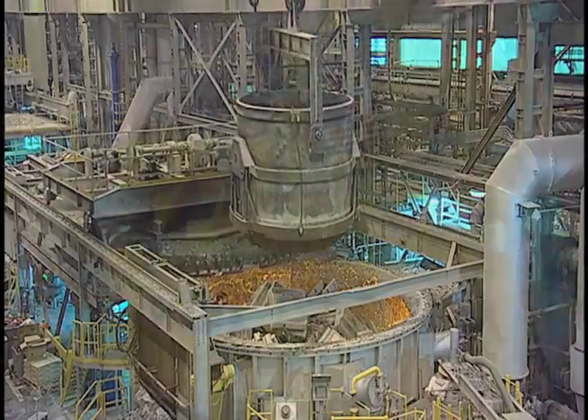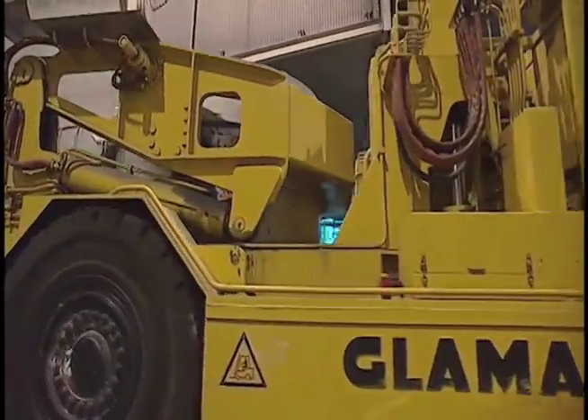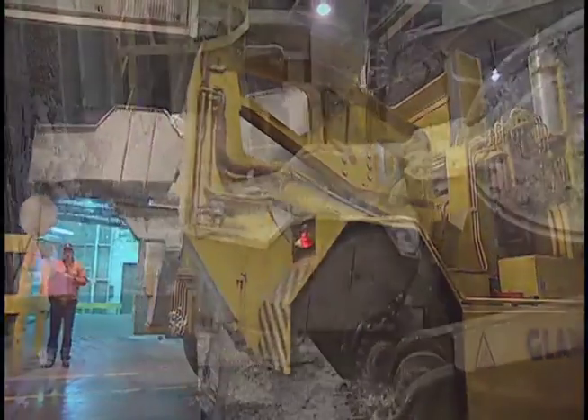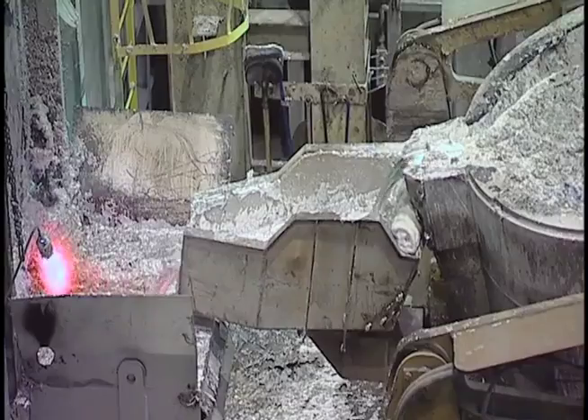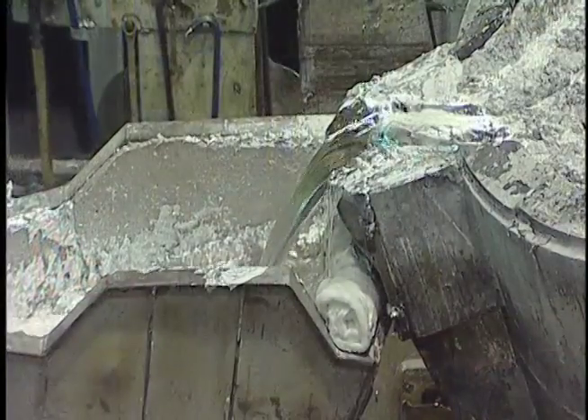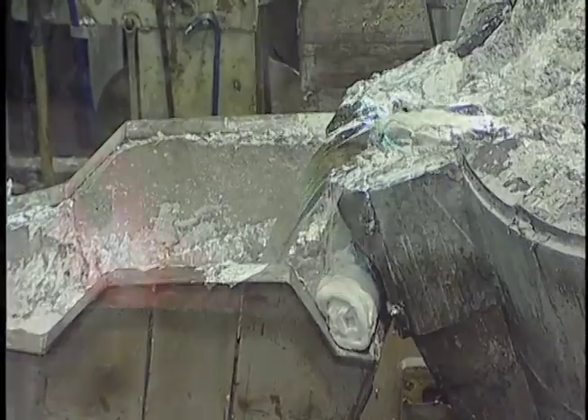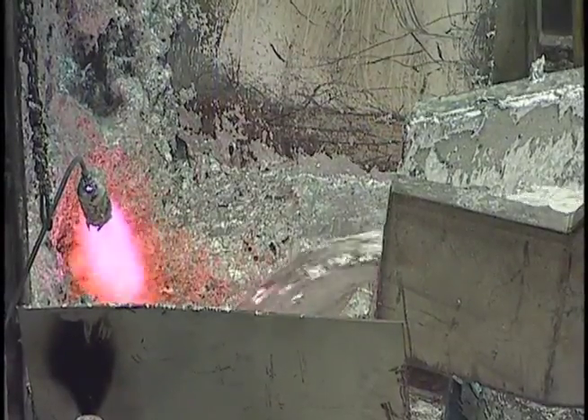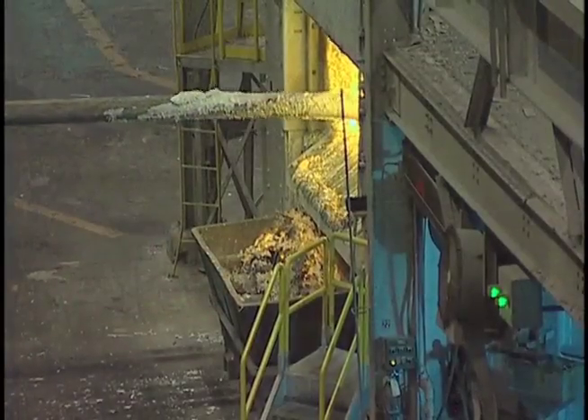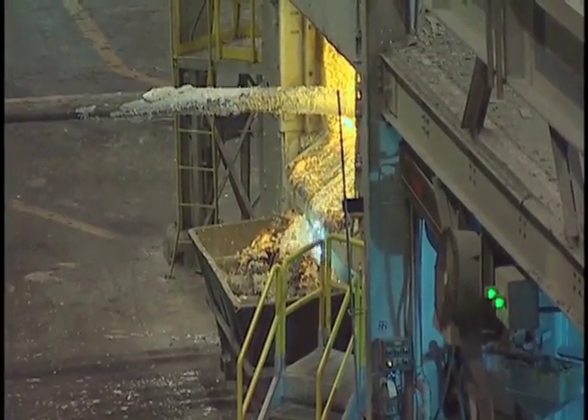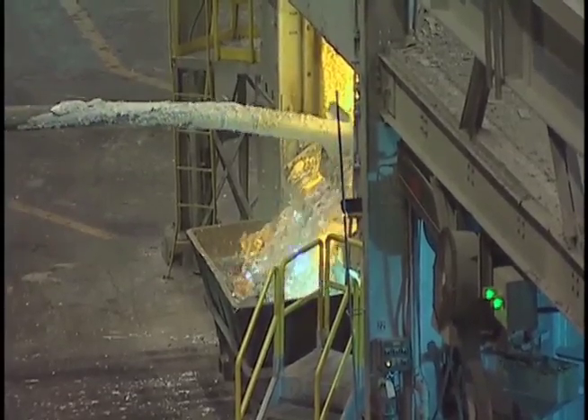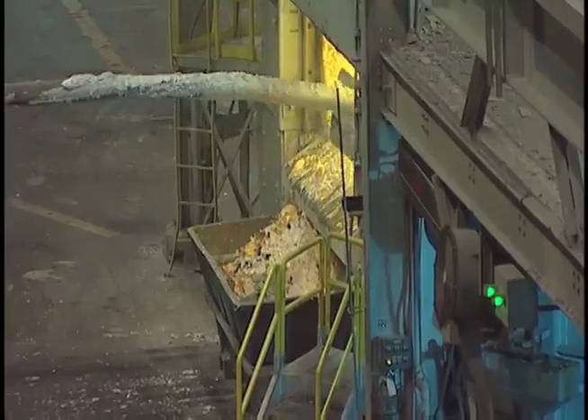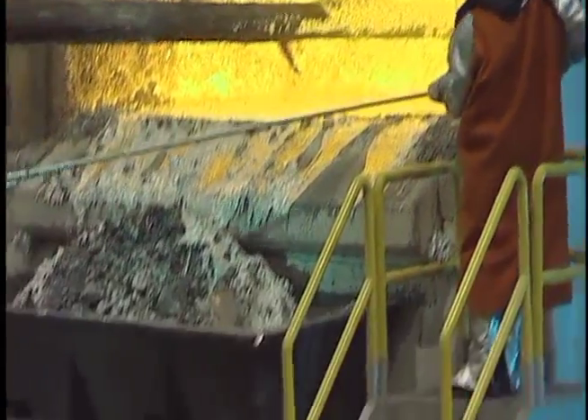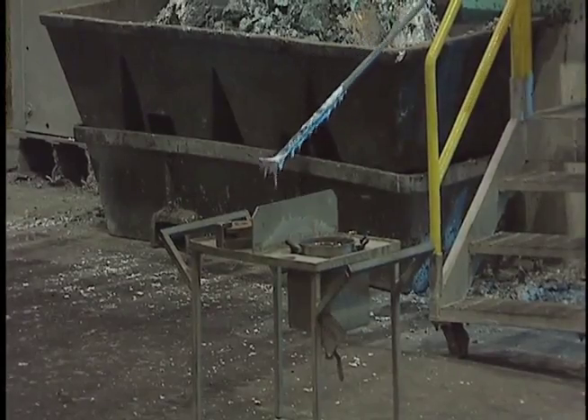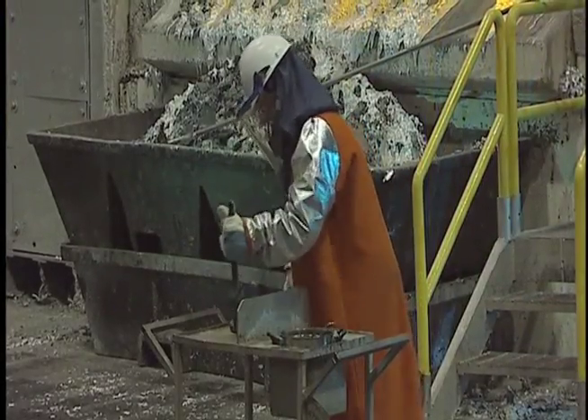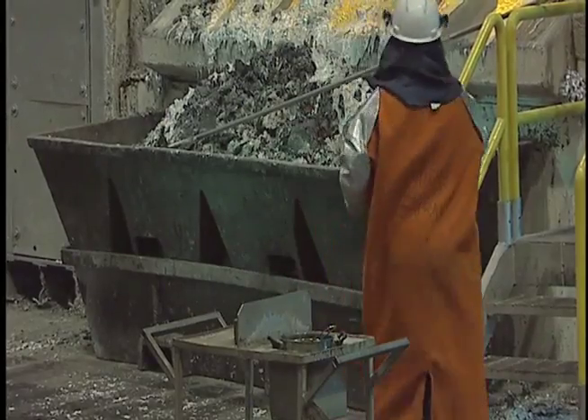To assist the melt cycle times, molten metal is brought in from the recycle center and swarf furnace and added to the melter. Once the desired molten temperature of 1,375 degrees Fahrenheit is achieved, the metal processing step begins. Oxidized impurities, called dross, are skimmed off the top of the molten bath. The chemical composition is then tested and can be adjusted to meet customer specifications by adding hardener elements such as copper, manganese, and magnesium.